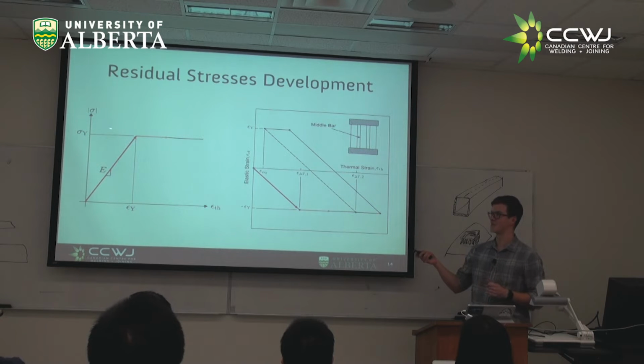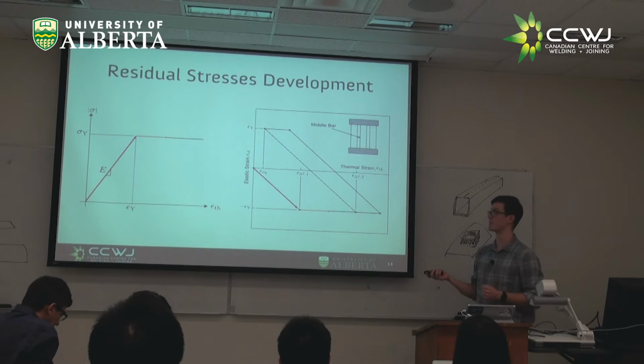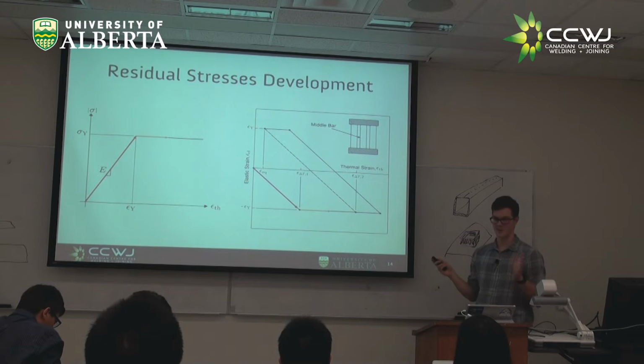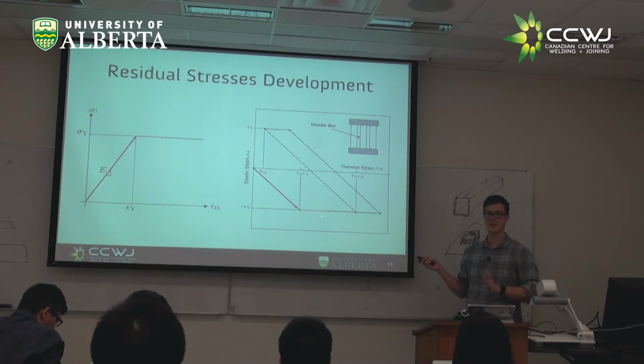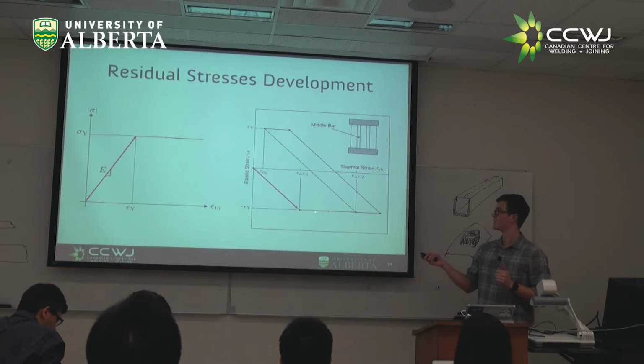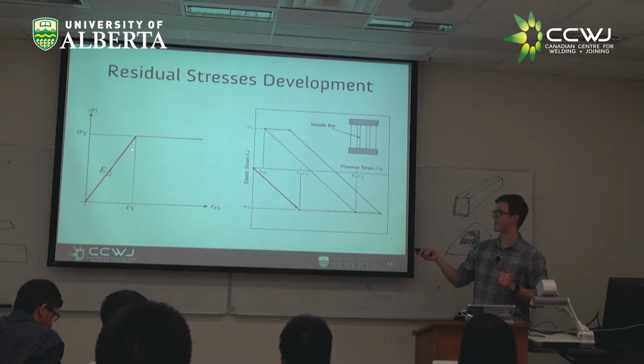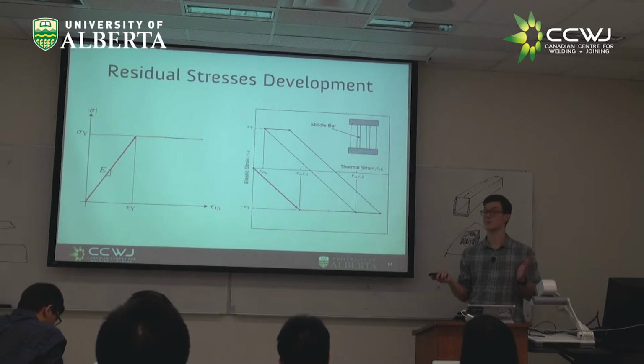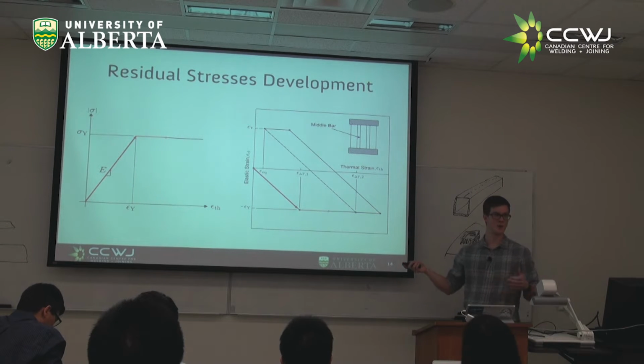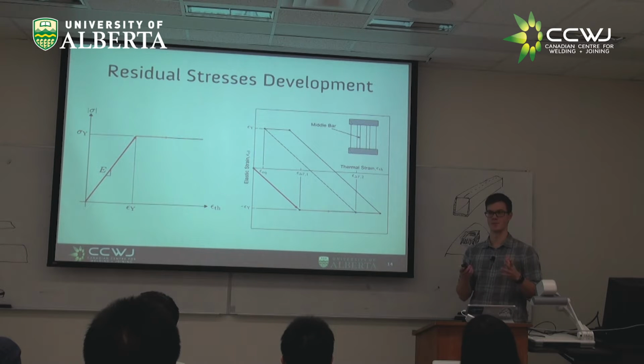So what happens next, looking at this graph, is hopefully what you guys imagine. Now, if we're elastic, perfectly plastic, we're going to start to yield. So although we keep adding more thermal strain, our elastic strain, which is here, and our stress can't change. This is what happens when you're yielding an elastic, perfectly plastic material. So we end up moving in a straight line. Now, we said that this is not a perfect representation of a real material, but we're going to see that this is fairly reasonable. Now, from this point on, this is typically where, if you have a stress strain curve, if you're doing material testing, this ends up being where you either end up pulling this to failure, or you take it back to the initial zero stress level.